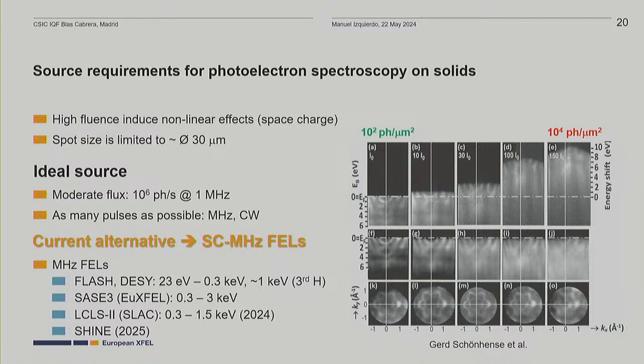And in the soft X-rays, the only possibility of realizing this today is by using superconducting free electron lasers that allow producing pulses with megahertz repetition rate. What possibilities are there? So the first one that was available is FLASH, but it barely reaches the soft X-rays, because basically in first harmonic you can go up to 300 electron volts. If you use third harmonic, you can reach up to 700, 800 electron volts, so close to 1 kilo electron volt, but not yet.